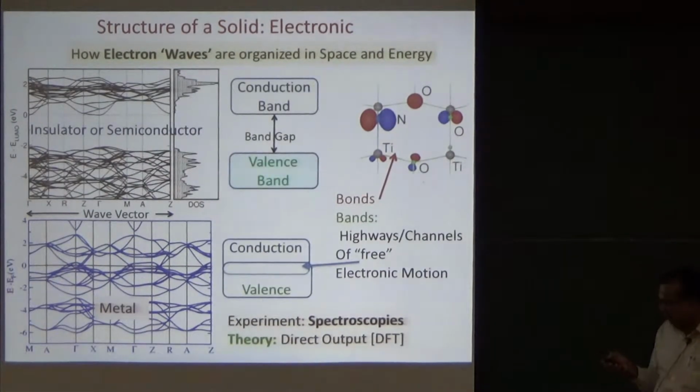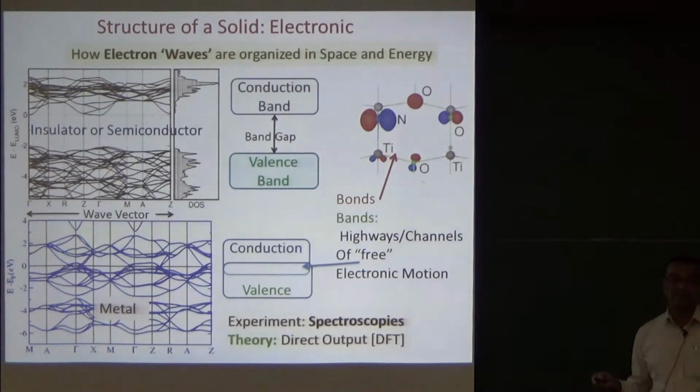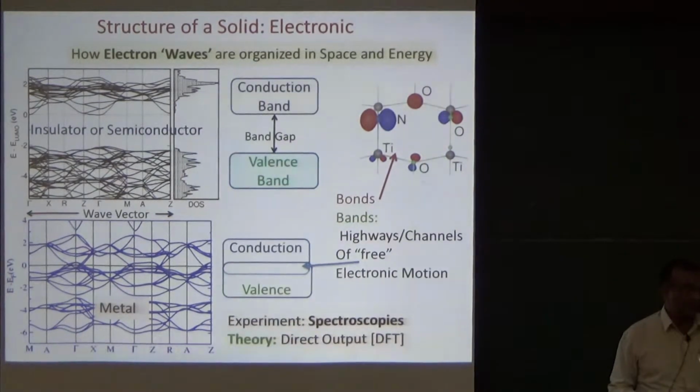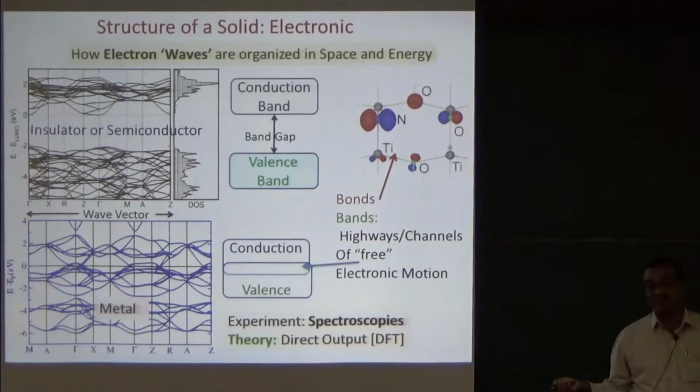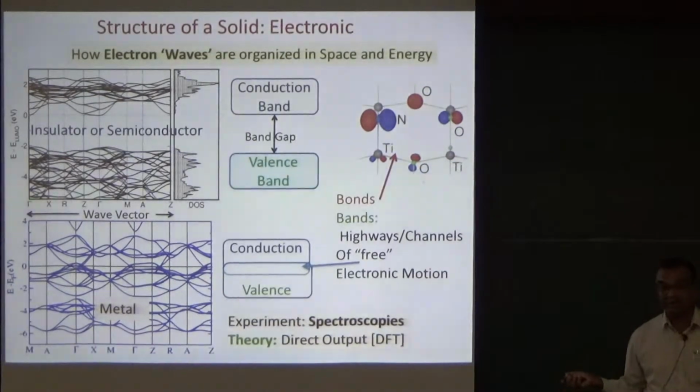The third level of structure is electronic structure, which people often call band structure. And this is one place where I should clarify that DFT methods are not band structure methods. Electronic structure comes out as a byproduct of a DFT calculation. The main target and success of DFT is actually the total energy function, which is what I have emphasized so far. Okay.